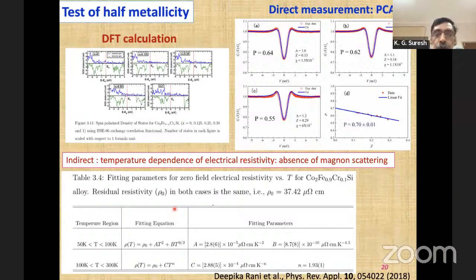For example, there are usually the collective excitations called the magnon excitations at low temperature for almost all the ferromagnets. Magnon excitations correspond to spin up and spin down, because you are actually going from a spin up to a spin down ultimately because of this excitation. Therefore, if you are actually getting a magnonic contribution, that means that you have spin up and spin down electrons close to the Fermi level. Therefore, that cannot be a gap at the Fermi level because they are gapless excitations. So if there is an absence of this magnonic contribution, represented by, let's say, the T square term, which is an indirect evidence telling that there is no magnonic contribution, therefore you can expect that one of the spin channels is missing, and therefore it has to be a spin polarized band structure.